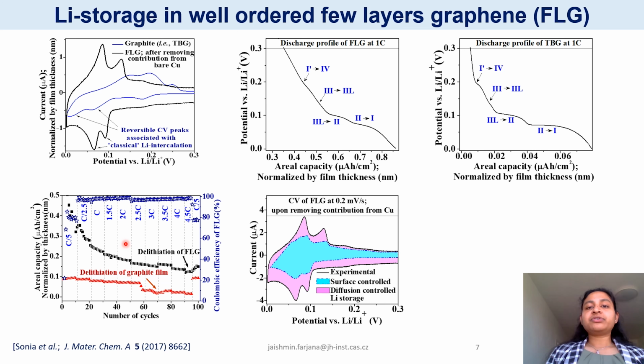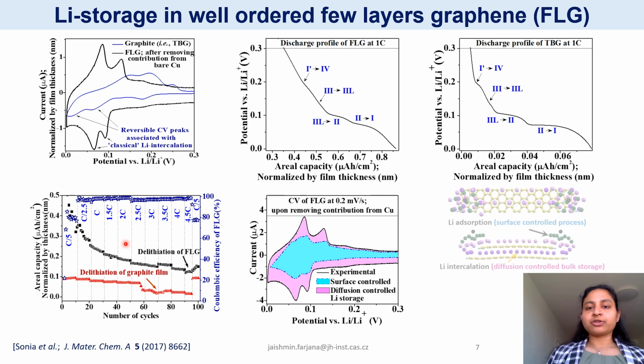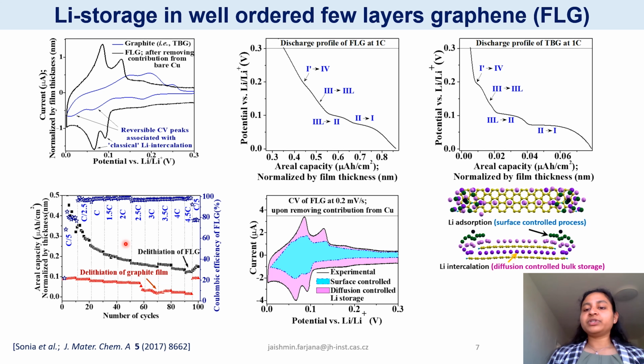But the difference comes when we check the specific capacity. The capacity for the few-layer graphene is 3 to 4 times higher than that of the graphite. So there must be some source of extra capacity storage in this few-layer graphene. We tried to search for that. We did the analysis of CV and we did DFT-based calculations, which indicated that there can be formation of more than one lithium layer on the surface of graphene and also at the stepped edges, which is a kind of surface-controlled process of lithium adsorption, and along with it there is some lithium intercalation, the classical one, which is the diffusion-controlled storage.